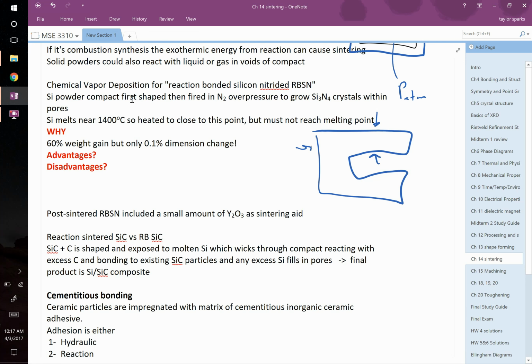We normally think of silicon nitride decomposing at these temperatures, but because you have a constant overpressure, it's actually going to form silicon nitride, right? And so everywhere that you had these interstitial sites between the silicon particles, that's going to get filled in as these things slowly grow. Is there a downside to this?